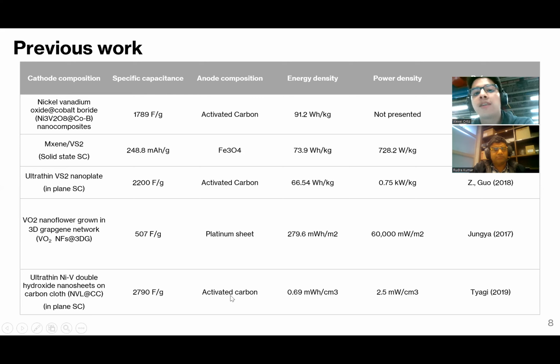This is because activated carbon is the most employed anode in research and in industry, and that is one of the reasons that the energy density is not high enough, because activated carbon has a lower capacitance than the cathode, making the whole capacitance of the electrode lower by a considerable amount. Well, here we have another cathode composition that is a MXene with VS2.